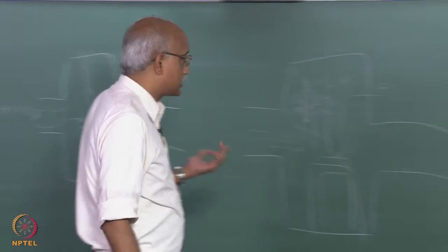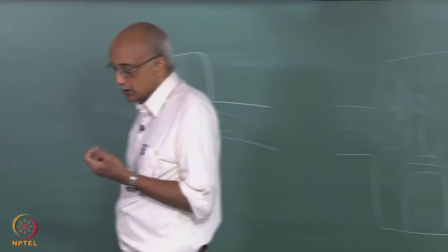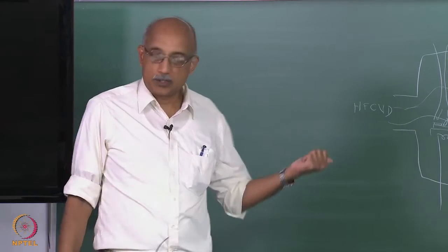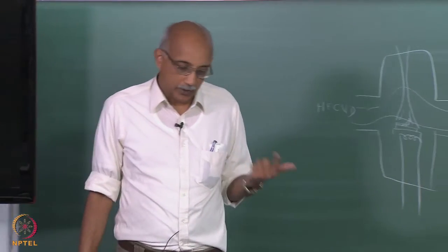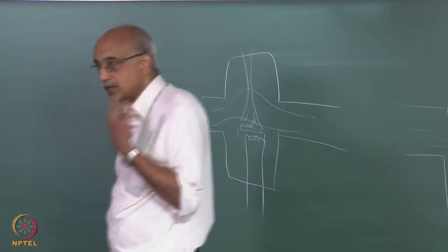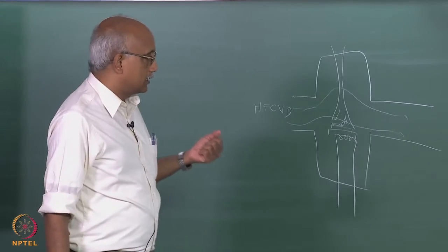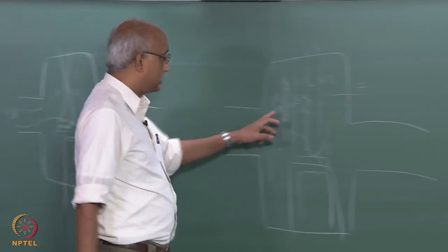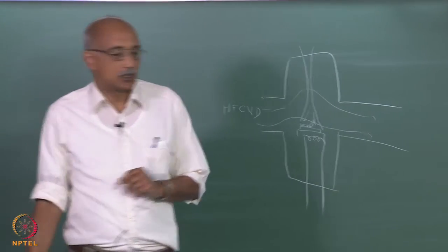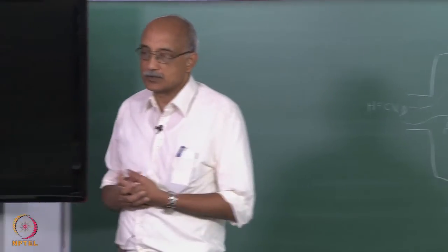If you are trying to optimize the deposition efficiency, you have to, A, make sure that you are providing a path for the feed molecules to encounter the hot filament, and B, you have to make sure that you are operating the filament under conditions that cause as complete a dissociation of the molecules as possible. And finally, you also have to make sure that you provide a transport path for the dissociated molecules to come and strike the substrate, right. So, all of these go together to establish the overall true efficiency of the system.